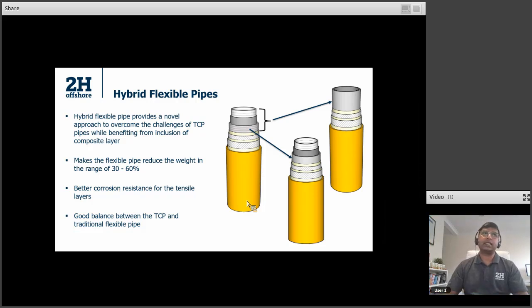So what happens is by eliminating part of steel, we reduce the weight and we can achieve a weight reduction in the range of 30 to 60% with these hybrid flexible structures. And also, it provides better corrosion resistance against some of the reservoir gases. And it provides a good balance between your traditional flexible pipe and TCP structures.